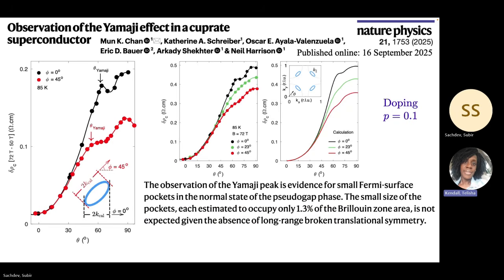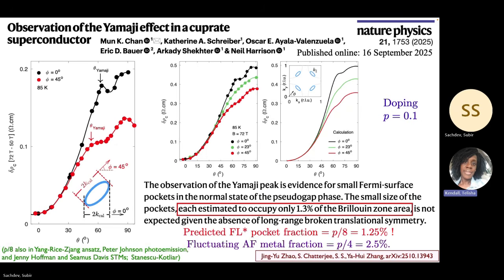Okay, then going on, the small size of the pockets, each estimated to occupy only 1.3% of the Brillouin zone, is not expected, given the absence of long-range broken translational symmetry. Well, okay, I will say, we did expect it, but most people didn't. But also very interesting is the size. They say the size is 1.3%. And we predicted p over 8, which is 1.25%, 20 years before the experiment. Or not 20, 15, I think.